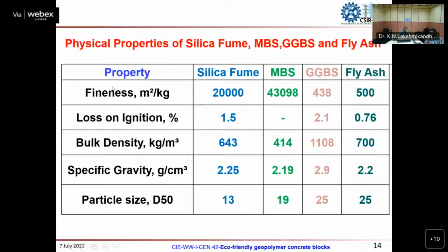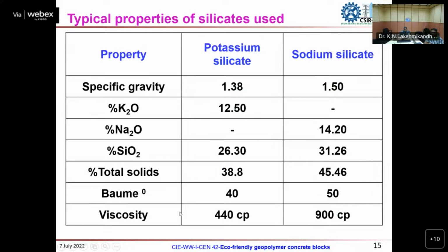But when you look at the fineness, it is different. So we have to see all these properties when you are formulating the mixes. And even though it has a similar particle size, there is a change in specific gravity. So all these factors we have to look at carefully. Again, when you are talking about the silicates used, commonly we are using sodium or potassium based silicate. And the main thing we have to see is the Na2O and SiO2 content. Generally we will go for about a 0.6 to 2 ratio or something like that.